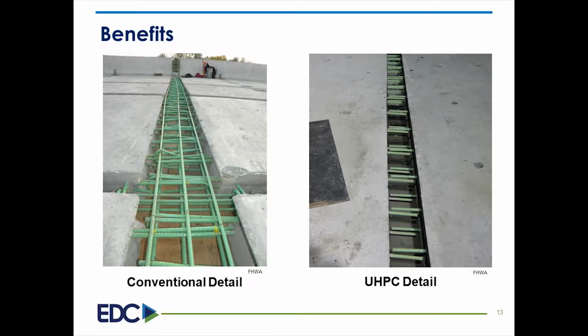So here, we compare a connection made with conventional concrete and a connection made with ultra-high performance concrete. These connections are in a precast deck panel, full depth bridge deck panel. Conventional concrete needs more rebar and more concrete for the connection than ultra-high performance concrete. And not only is there less concrete and less rebar with the ultra-high performance concrete, very importantly, there's less congestion. Also with the ultra-high performance concrete, using the guidelines that are available, you don't need to have contact lap splices. So with fewer pieces of rebar that don't need to be in a contact lap splice, we can get less interference in our connections.